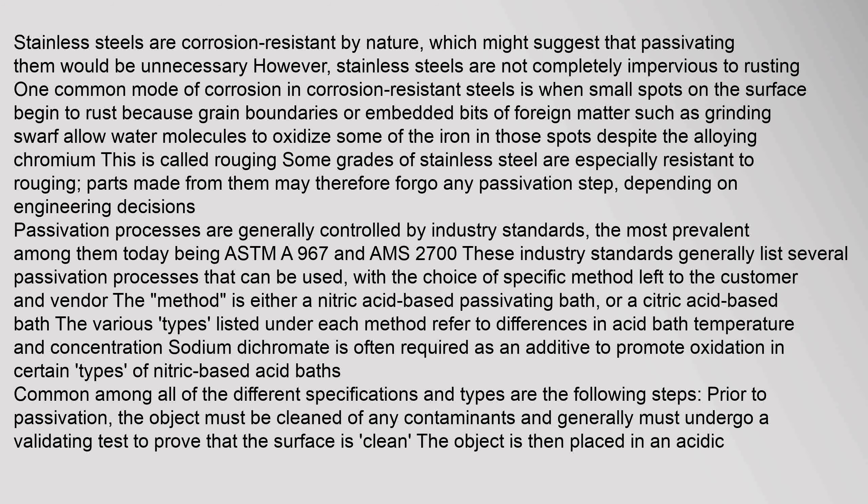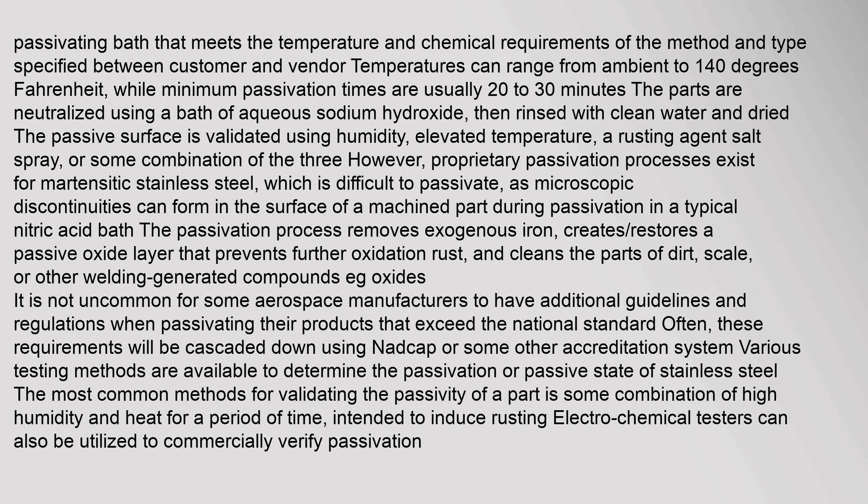These industry standards generally list several passivation processes that can be used, with the choice of specific method left to the customer and vendor. The method is either a nitric acid-based passivating bath or a citric acid-based bath. The various types listed under each method refer to differences in acid bath temperature and concentration. Sodium dichromate is often required as an additive to promote oxidation in certain types of nitric-based acid baths. Common among all specifications are the following steps: prior to passivation, the object must be cleaned of any contaminants and generally must undergo a validating test to prove the surface is clean. The object is then placed in an acidic passivating bath meeting the temperature and chemical requirements specified, with temperatures ranging from ambient to 140 degrees Fahrenheit, and minimum passivation times usually of 20–30 minutes. The parts are neutralized using a bath of aqueous sodium hydroxide, then rinsed with clean water and dried.